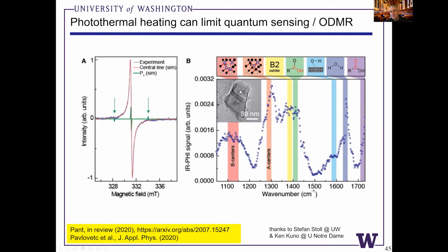This vibration region has been correlated with A centers, sort of nitrogen aggregates. We see some enhanced absorption in the diamonds that could be indexed to carboxylic acid groups or hydroxyls potentially. There are also some other carbonyl or water absorption. We have carbonyl and water absorption bands.